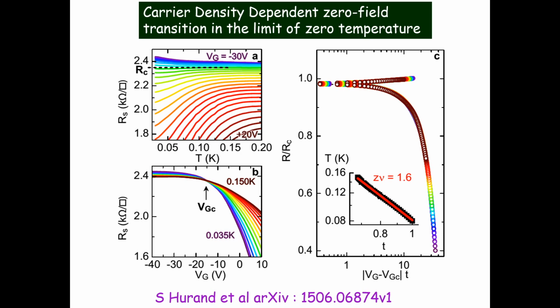One can do a scaling analysis of this also. So, this is the superconducting part, the positive gate voltage, this is the non-superconducting part, and this is the universal crossing point, V_GC, happening at this point. So, you can collapse the data. It is a nice collapse for the gate voltage below which we have superconducting state, and this is the negative side of the gate voltage where we have non-superconducting state. And you look at the exponent zν, it is 1.6, which we got again in the earlier magnetic field driven transition at very low temperatures.